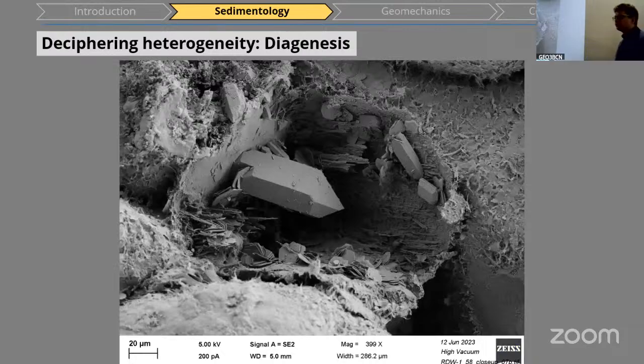We also find a lot of later processes. So these cutans formed very early on, right after the sand grains were deposited. But here you can see the remnants of a grain. So you can see the grain cutan, these clays, they're still here. But the actual feldspar grain, which used to be there, has been dissolved. And instead you have formed quartz cements and some of these other clay minerals. And this is something that we see very commonly. And this is also one reason why these sands still have a very good porosity, because we have a lot of these dissolved grains, which then, of course, are very good because you can fill those with fluids.